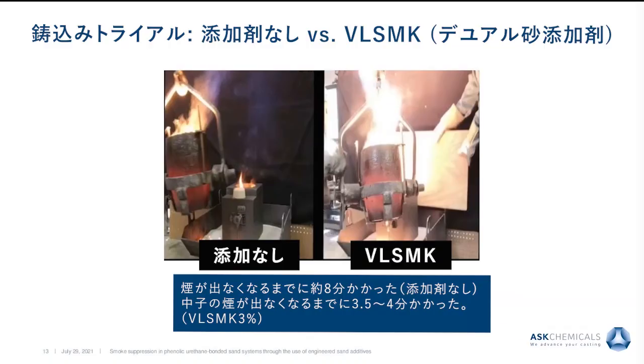Okay, so what you can see, and you just saw in the video, is that clearly there's no question that with the additive we can definitely suppress quite a bit of smoke. It took about 8 minutes, when we analyzed each of these videos, for the core with no additive to stop smoking, and it took about 3 to 4 minutes for the core to stop smoking in the presence of the additive. So that already gives you an idea that what we saw in the lab was in pretty good correlation with what we see actually in the foundry.